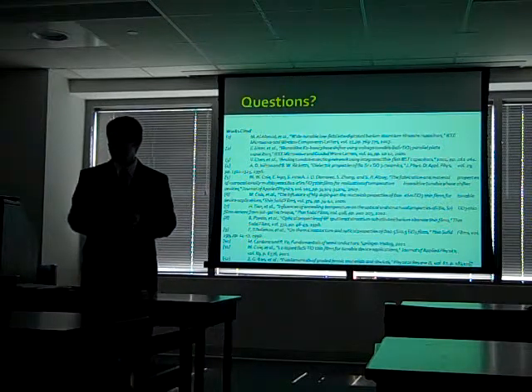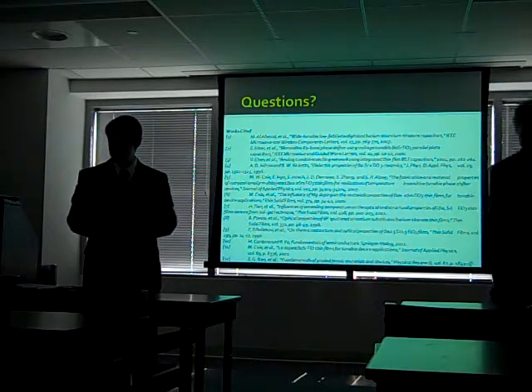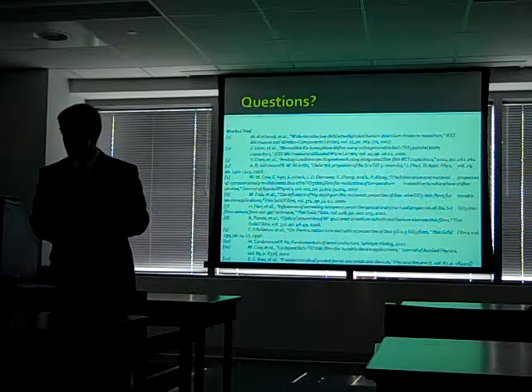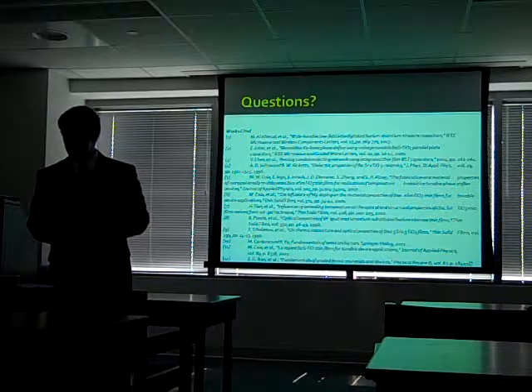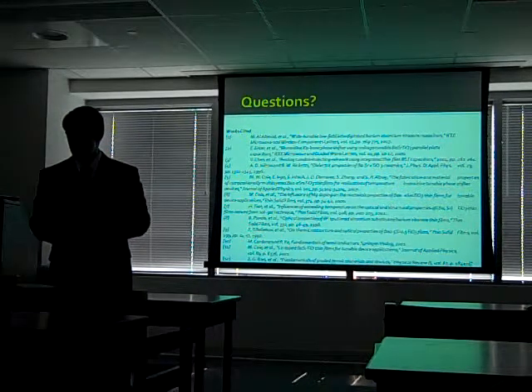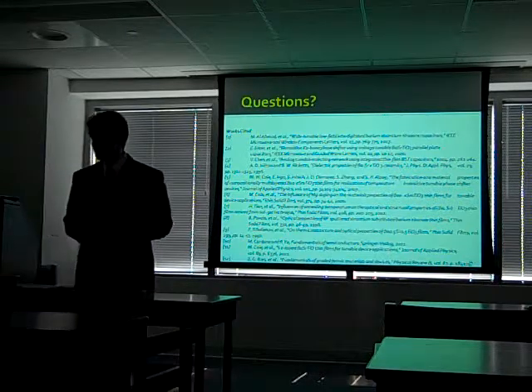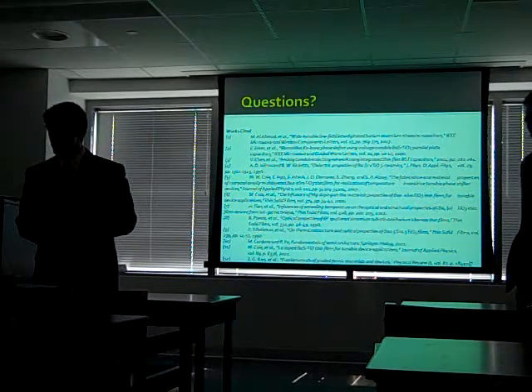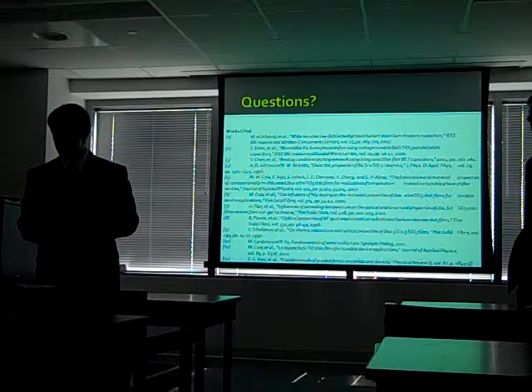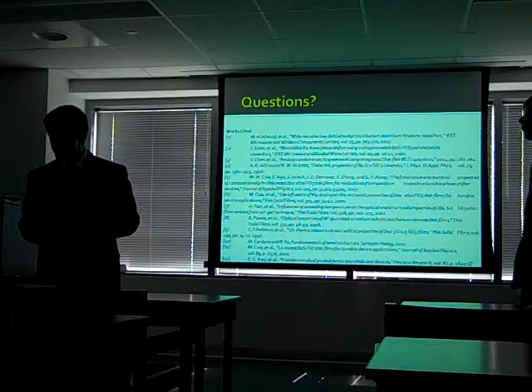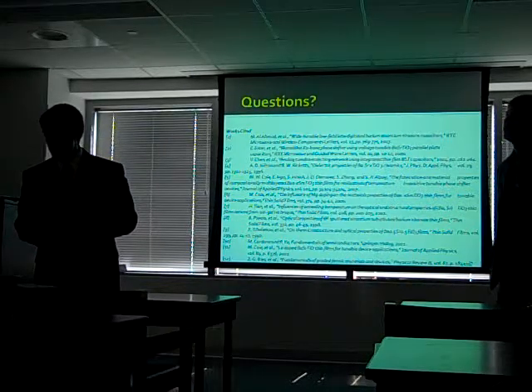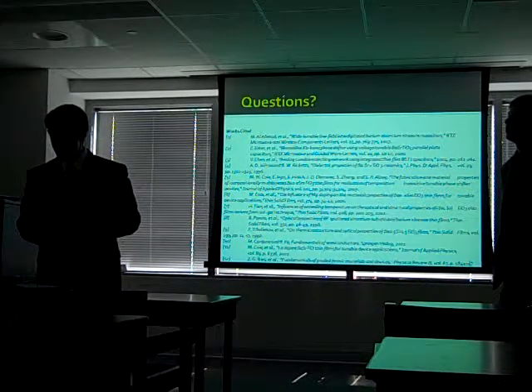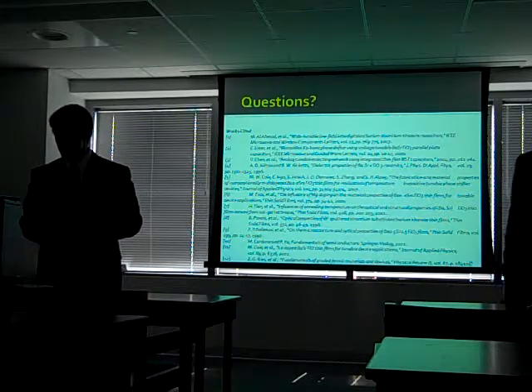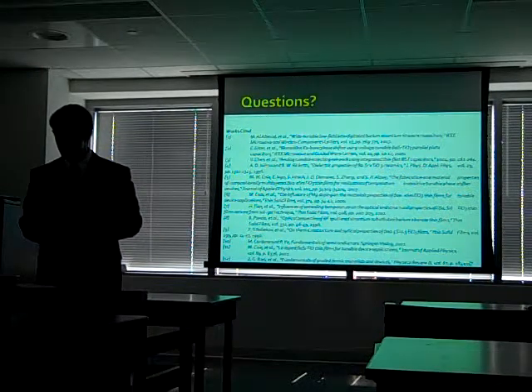You addressed the issue with diffusion between the layers, and you said that even if it's a multi-step annealing, when you have the second layer, you also anneal the first with it, right? Right. You still have some trouble with diffusion. So my question is, when you analyzed it and did the TEM cut, the FIB cut, is there a risk that with the FIB you introduce enough heat to again induce diffusion? So the question is, what do you in the end really see? Is that what you really tested, or is that what was induced in the FIB?